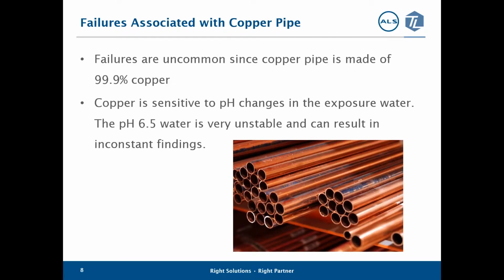Failures for copper pipe is also very uncommon. Copper is made of 99.9% copper, so there's little chance that the copper pipe or fitting could fail for anything other than copper. There have been problems with copper extraction in the past when products were tested using pH 6.5 test water because the water was unstable and the pH drifted downward during the test. This change in the pH during the test resulted in a corrosive water condition that would cause copper to be etched from the pipe surface.